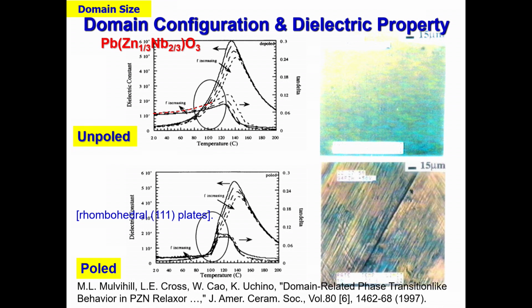Unpoled, as you're familiar with, relaxation and the dielectric loss is quite large around here, around room temperature. However, once we pole, at room temperature, this is stabilized. In that case, we found that the relaxation totally disappears, and the dielectric tangent delta is almost one order of magnitude smaller. So very low loss happened.